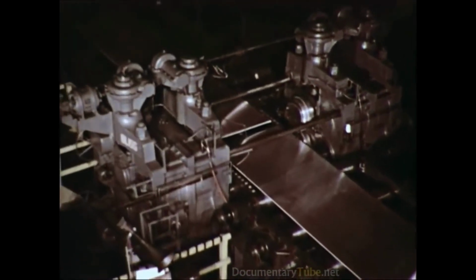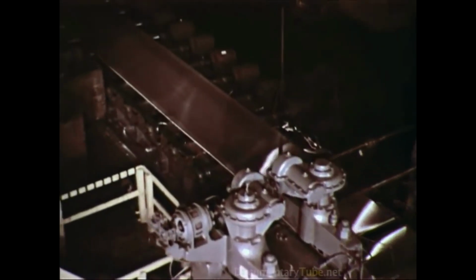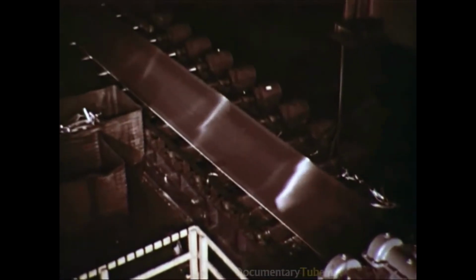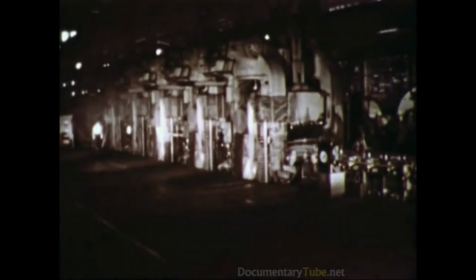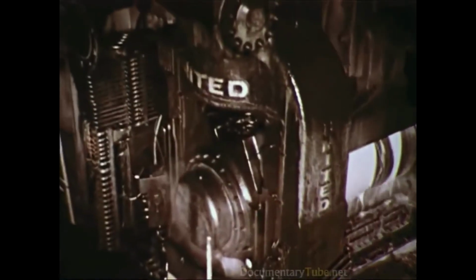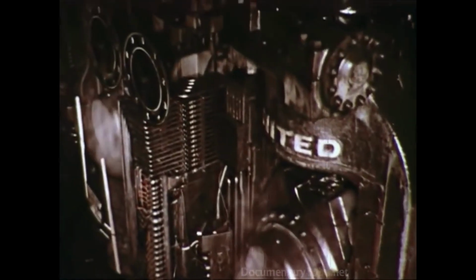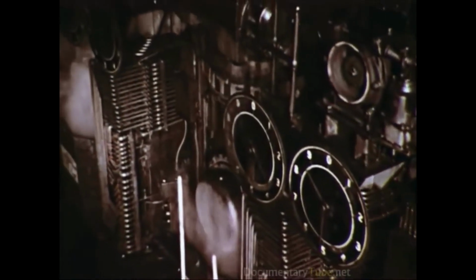As the rolling process continues, the slab is reduced from 3 inches down to 7/8 of an inch in thickness, and its length is increased from 30 to 125 feet. The slab then moves into a huge 5-stand continuous mill. Actually, it is 5 mills working in tandem to reduce the 7/8 inch slab down to sheets of 1/10 of an inch in a single pass.